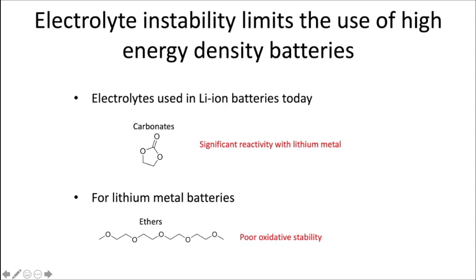And then the other class is ether-based. They can give reasonable stability for cycling with lithium metal, but the oxidative stability for this class of electrolyte solvent is poor. It tends to have oxidative decomposition reactions at the cathode side.